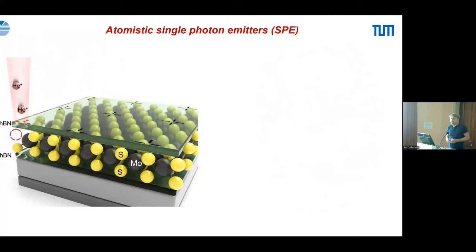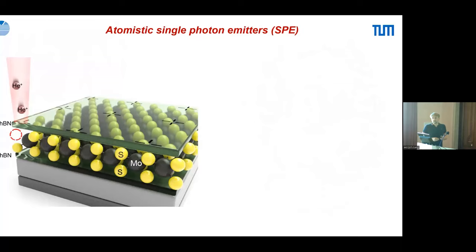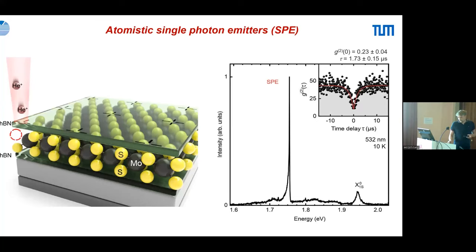This talk is about heterostructures made out of 2D materials — predominantly MoS2. We use a gentle focused beam of helium ions, and by the interaction with the molybdenum disulfide we kick out sulfur atoms, which turn out to be luminescent centers. Everything is encapsulated in hexagonal boron nitride to optimize the optical properties, as everyone has been doing for almost 10 years.